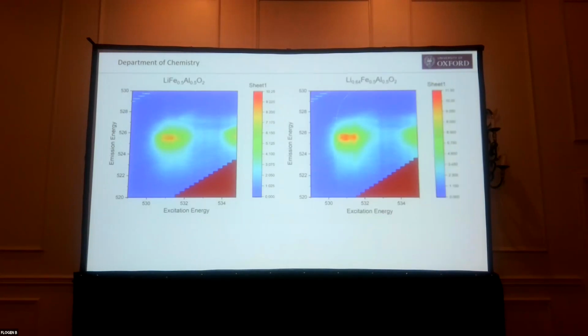And I hope, showing you this is the oxidized material, I hope you can see that there is something there. There's an extra emission, or enhancement of emission, in this specific area, which is consistent with oxidized oxygen. And we can reinforce that idea by doing, rather than a total integration, a partial integration of this low energy region. So this is what the pristine material looks like, and this is what the oxidized material looks like. You can see this here would be consistent with the emission from these oxidized oxygens.